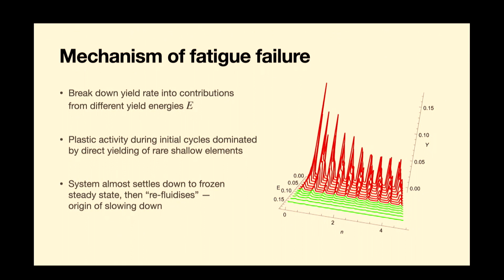So let's look a little bit more at the mechanism of fatigue failure. I've plotted for you here the yield rate as a function of number of strain cycles, and broken down into the contributions from the different yield energies. Okay, so that's why this is a three-dimensional plot. What you see is that in the first cycles, which is over here, some very small n, all of the yielding basically happens in the elements that have got low yield strains. And that makes sense, because those are the things you break immediately, you make them yield, right? And they become more stable after that, at least statistically speaking, right?